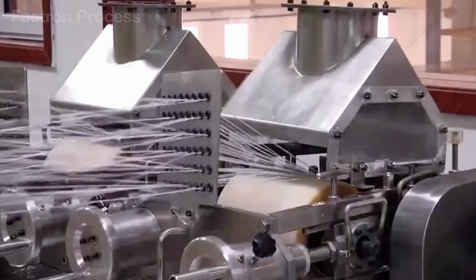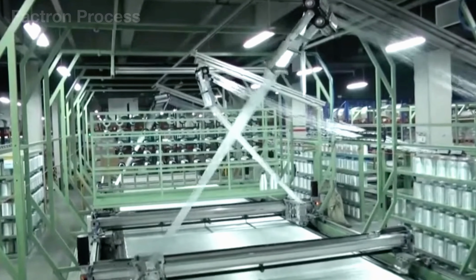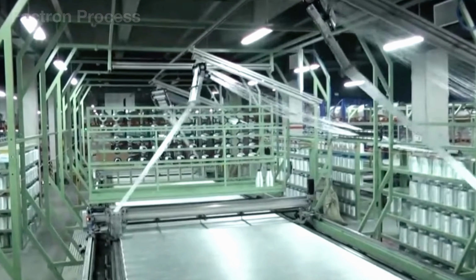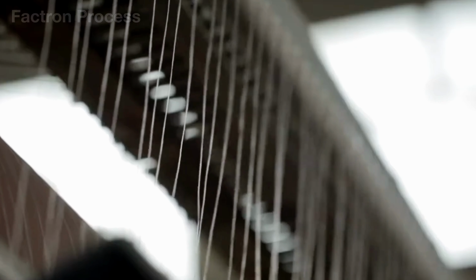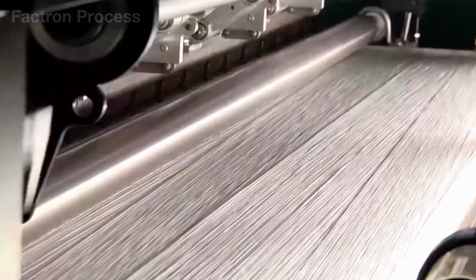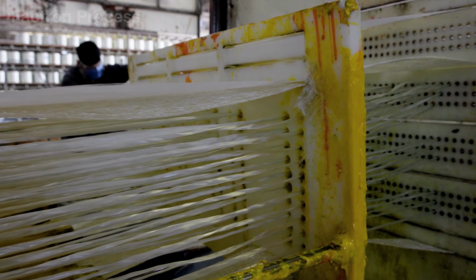Below, high-speed winding equipment rotates at roughly 3,000 revolutions per minute, pulling the glass into fibers only a few micrometers thick. For comparison, the average human hair is about 70 micrometers in diameter, while these fiberglass filaments measure only a small fraction of that size. Almost immediately afterward, low-pressure water sprays cool the fibers within moments of formation.